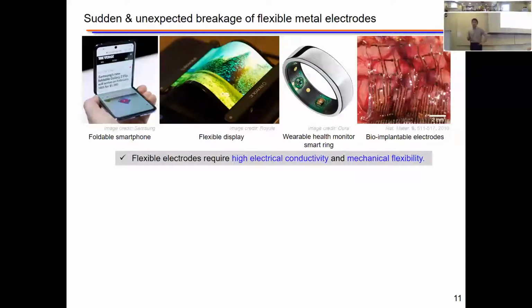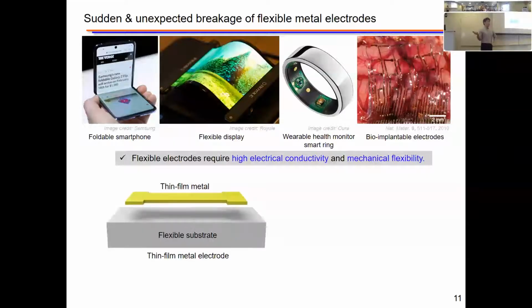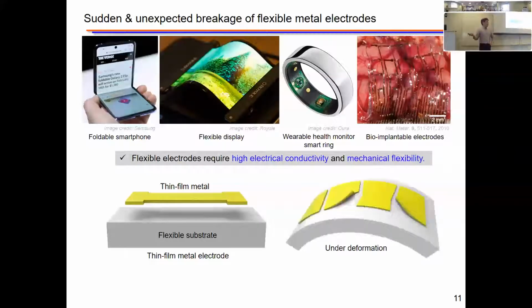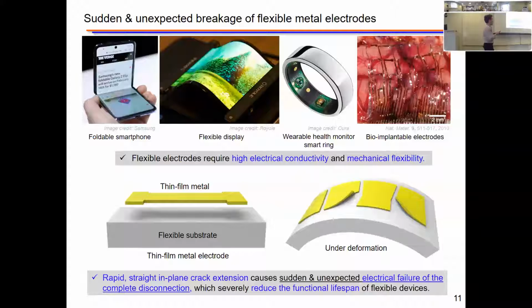We're interested in flexible electrodes, which have been considered an essential component that opens up all kinds of new possibilities for electronics, spanning from our daily devices like smartphones and displays, to wearable health monitoring devices, and further offering opportunities for diagnostics on curvilinear interfaces. Ideally, a flexible electrode requires high electrical conductivity and mechanical flexibility. In this regard, thin film metal on a flexible substrate has been ubiquitously utilized for advanced flexible and wearable electronics. However, during practical use, we often experience unexpected failure of the device, and it becomes frustratingly unusable. Because of the brittle nature of metal, rapid surface cracks develop under various deformations. After the onset of metal fracture, in-plane crack extension across the metal filament causes catastrophic failure by complete disconnection, severely reducing the functional lifespan of devices.